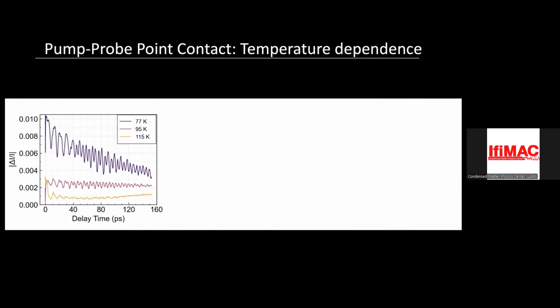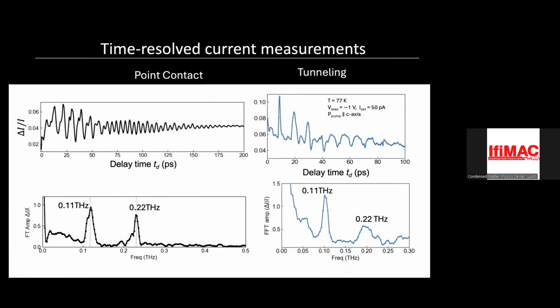Okay, so now let's do temperature dependence, right? First, you should already be intrigued. Prior work had one mode at 0.23. We're seeing two modes, one at 0.11 and one at 0.22. And you can already see from here that these two are almost the same amplitude. So it's not as though one is the harmonic of the other.